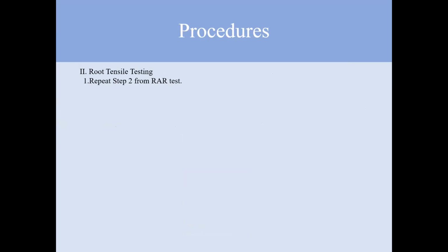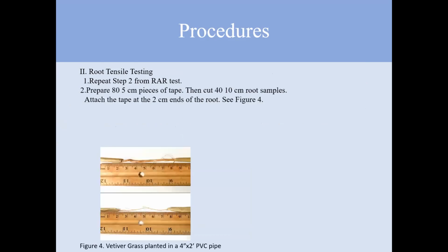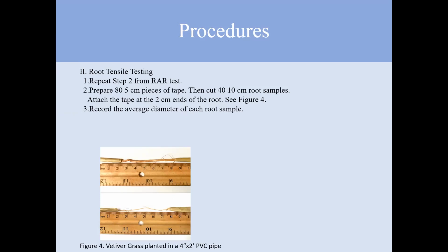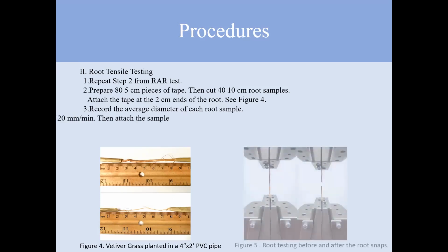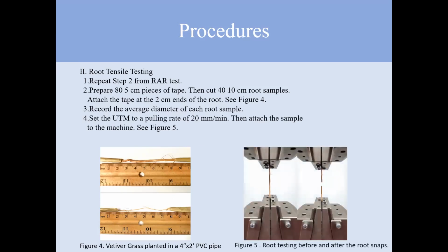Now to do the root tensile test, we used a second vetiver grass and repeated the same method as the RAR test in removing the root system. We prepared 80 5-centimeter pieces of tape and we cut 40 10-centimeter root samples and attached the tape at the 2 centimeter ends of the root. We recorded the average diameter of each root sample. Before we attached the root, we set the UTM at a pulling rate of 20 millimeters per minute, and then we attached the samples to the machine. Once the root snapped, we recorded the peak load.